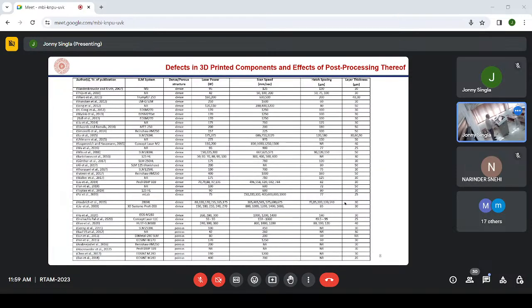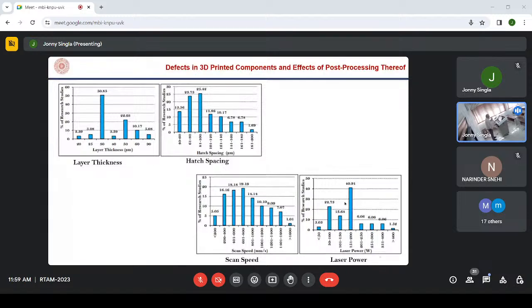So different researchers have used different energy density functions, right? Scan speed, laser power, hatch spacing, and layer thickness. And if you analyze this data and come to certain graphical conclusions, you will find that the layer thickness optimal value is 30 micrometer for almost all the materials. That means you have to choose the parameters of the AM technique in such a way that layer thickness should not be more than 30 micrometer and should not be less than 30 micrometer. So it is in the range of 30 micrometer.